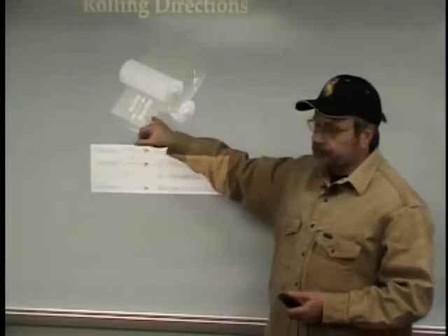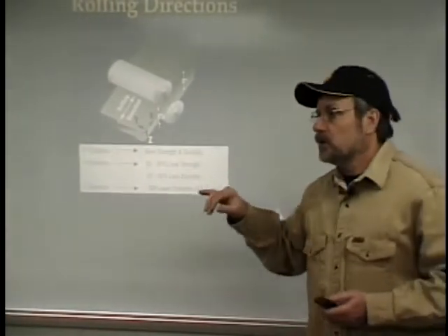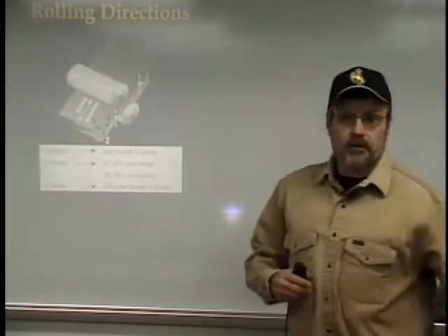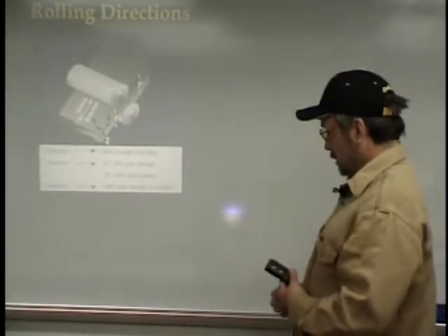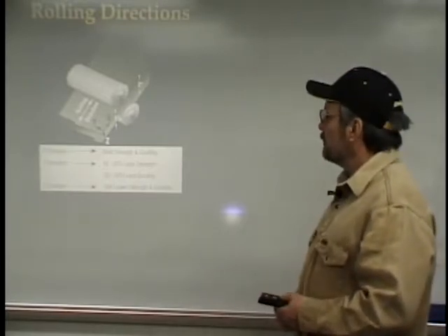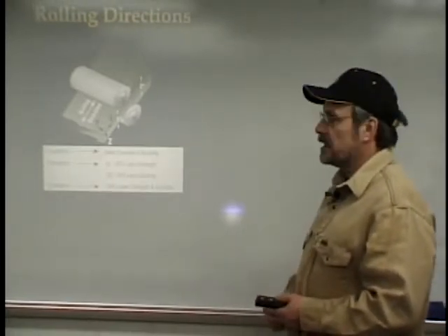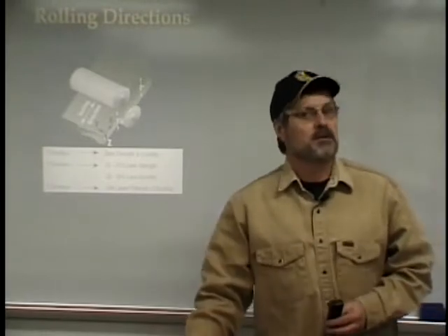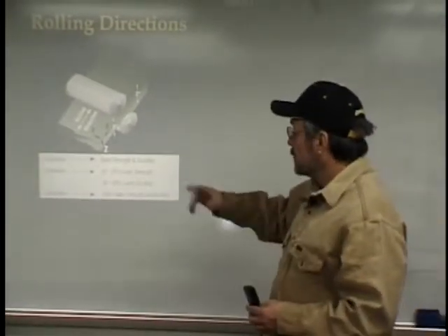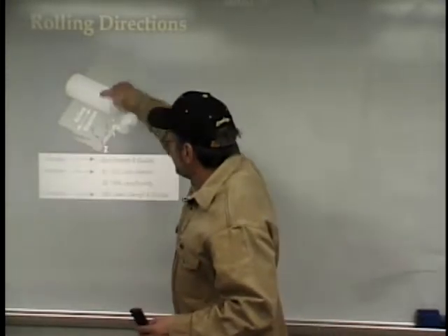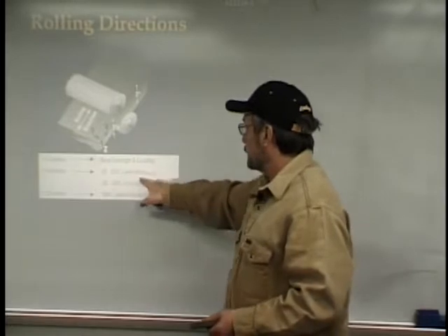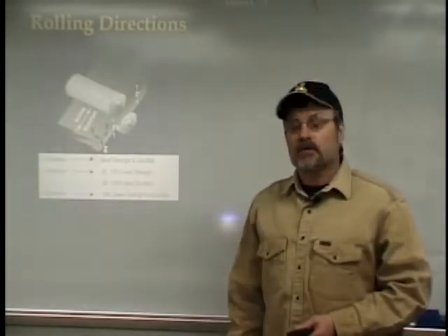I had a direct experience with this one time. I had to go up to Montana and test a bunch of welders, and their welds kept failing. And they kept failing, and they were good welds. They shouldn't have failed. And what I found on further inspection was that they had the test coupons ready for me when I got there. But what they had done, they had cut the test coupons this way. And so we flipped them together. We made the welds. Well, it had less strength and less ductility, and so they were failing.